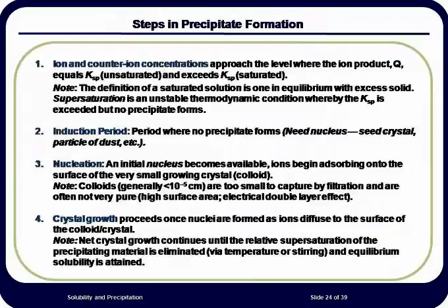The first nucleation site is where the KSP is exceeded. This usually occurs at the point where the precipitating agent drops touch the analyte solution. At this time, if the bulk concentration of the ions in solution were used to calculate the ion product, it would likely be less than KSP. However, the localized concentration of the ions is greater than KSP, where the drop first touches the solution. This approach to KSP can be slowed by vigorous stirring of the solution during the addition of precipitating agent.